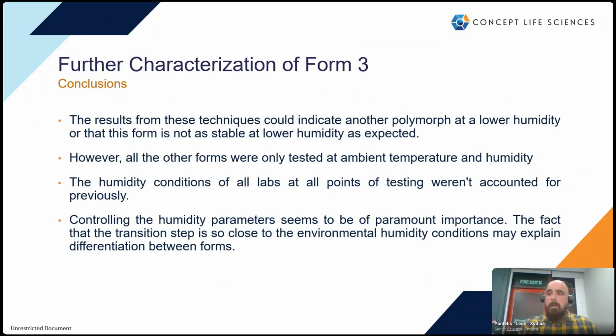We want to run a humidity-controlled measurement. Unfortunately, we are in the UK, and the synthesis was in the UK. We didn't take into account the humidity at those different measurements that we ran. Checking our Hanwell humidity systems, we have had humidities that range from 15 up to 65% relative humidity.